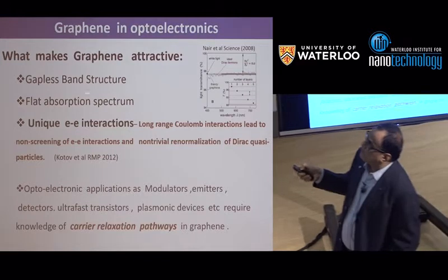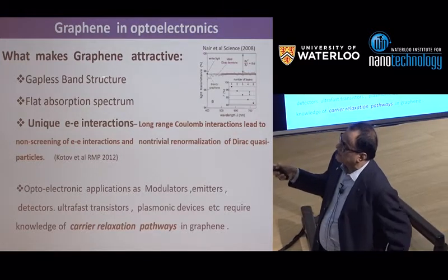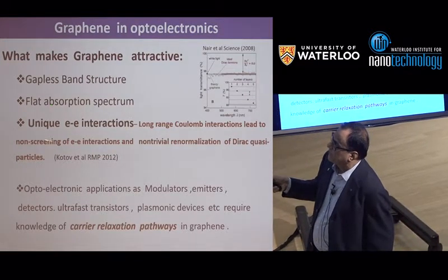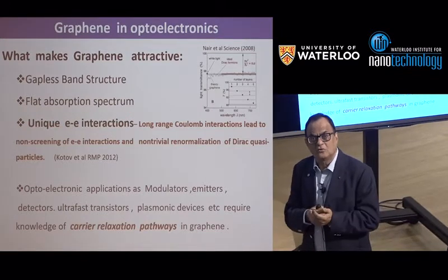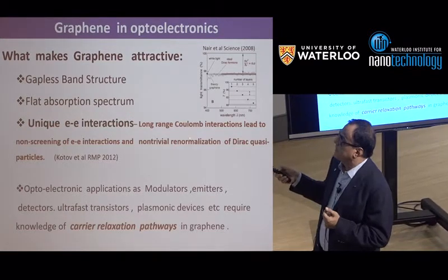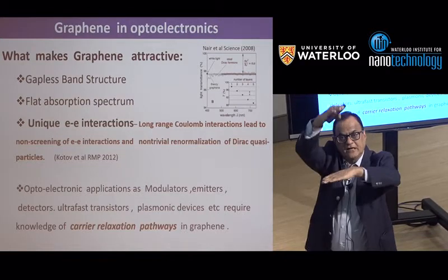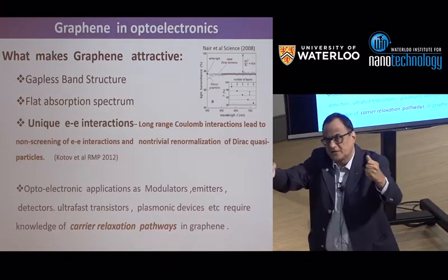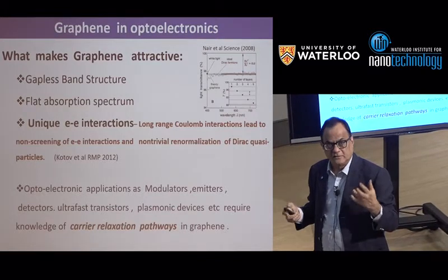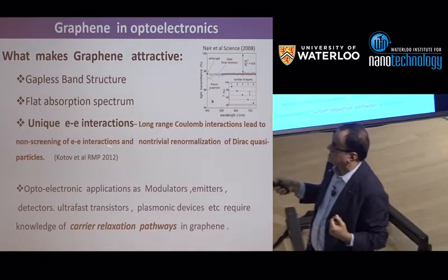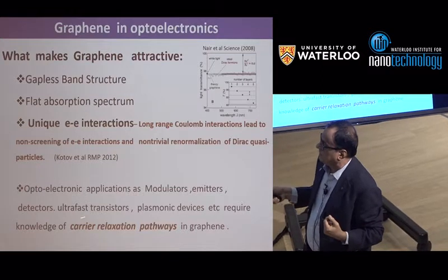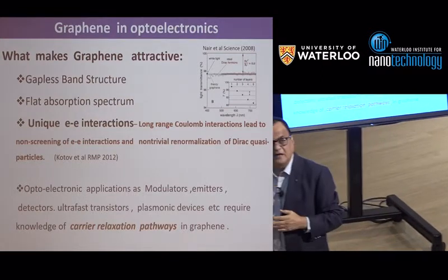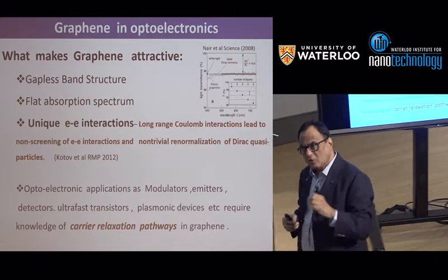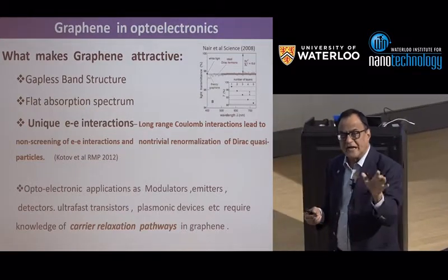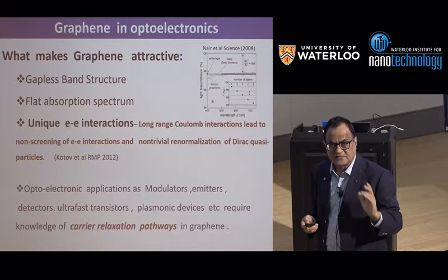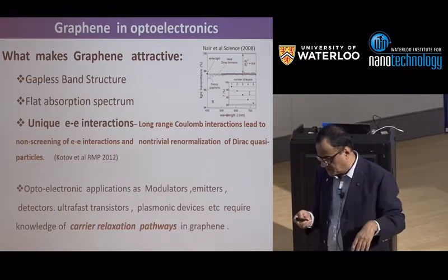So in particular graphene, as I said, has a gapless band structure, flat absorption, and also this unique electron-electron interaction, because the screening is very little because there is nothing below and above. So the electrostatic interaction is strong and it is not screened as much as in 3 dimensions. And our interest is to find out carrier relaxation pathways and quantitative numbers on the scattering cross section if we can. So that's the goal of the ultrafast community.